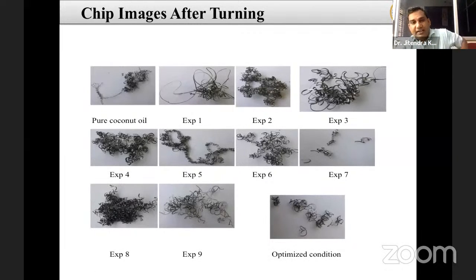Because we know that if we fabricate the discontinuous chip, then we can reduce the cutting forces and improve the surface roughness of the surface finish. For that reason, you can see that with this discontinuous chip we get lower forces and better surface finish. In the optimized condition it is also more or less a discontinuous type of chip, but still somewhat curly, with a very small chip thickness. It is most probably curly, but it is also a discontinuous type chip in the optimized condition.